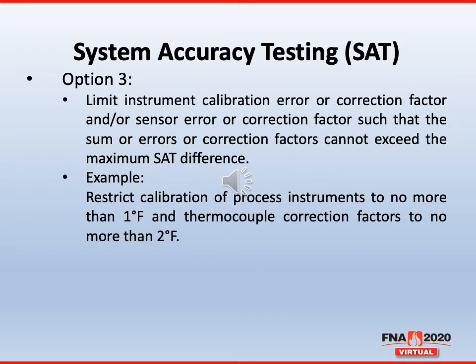And option 3, limit your instrument calibration error correction factors and/or the sensor error or correction factors so that the sum of the errors or correction factors cannot exceed the maximum SAT difference. For example, you restrict your calibration of your process instruments to no more than plus or minus 1 degree, and your thermocouple correction factors no more than 2 degrees. In the worst case scenario, your tightest tolerance for an SAT for a class 2 furnace is plus or minus 3 degrees. So if you restrict your calibrations to 1 and your thermocouple correction factors to 2, add those together, they're within 3. So that is the third option when it comes to the alternate SAT process.